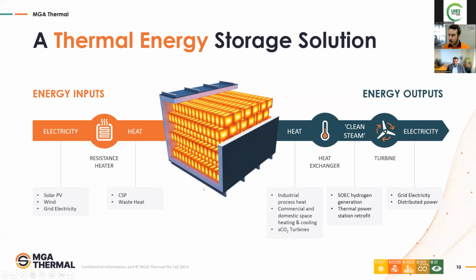So we charge electrically. It's using simple resistive heating to put energy into our blocks. We heat them up through the phase change. We can also accept waste heat from industry if it's at an appropriate temperature. And we discharge using an inert gas loop, which can then be connected directly to an industrial process, or it can be used to generate steam for either industrial use or for power generation. Our core product utilizes aluminium as a phase change material, so 660 degrees Celsius melting temperature, which is very convenient for making steam for a range of industrial processes, but also for power generation.